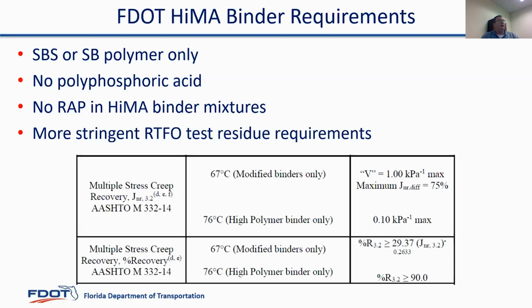And then obviously, how do we assure we're getting high polymer binder? It's the more stringent testing requirements on the RTFO residue that you see on the little table there. Again, it's tested at a higher temperature, and then it's got very strict, strenuous, JNR and also percent recovery requirements. We actually don't spec a percentage of polymer like you saw David talking about. We rely on the MSCR testing to assure we've got the product we want.